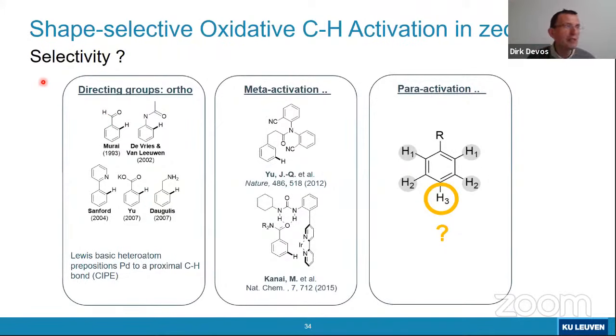We have shown already that MOFs can have beneficial effects regarding stability, regarding activity on a palladium catalyzed reaction, but there is still one elephant in the room, and that's of course the selectivity, the site selectivity of C-H activation reactions. And already many years ago, Murai, for instance, and also Hans de Vries and Piet van Leeuwen, did seminal work in the sense that they showed that if you have a directing group, then the C-H bond in ortho is quite easy to selectively activate.